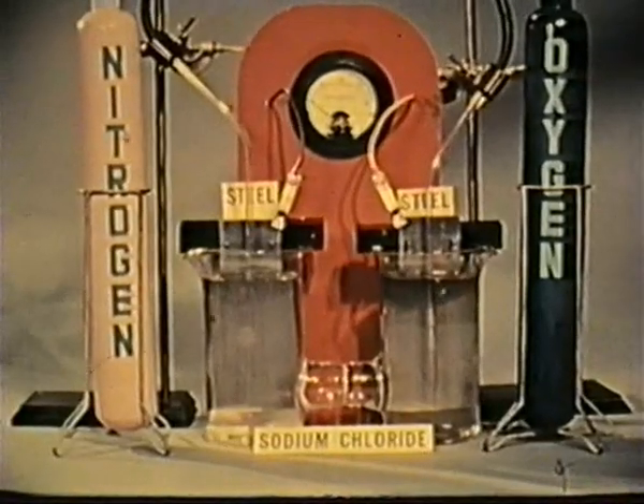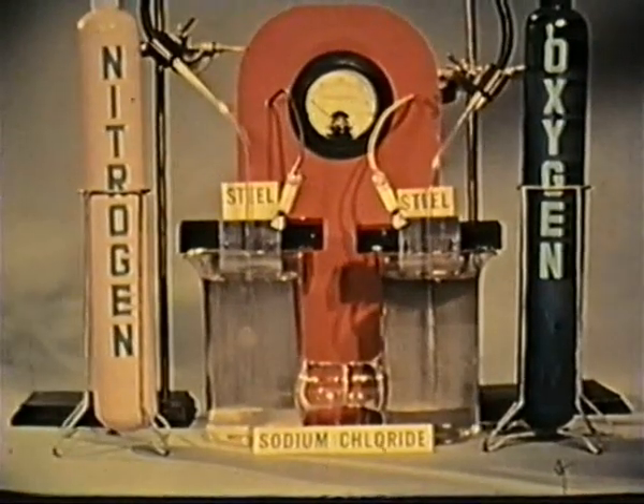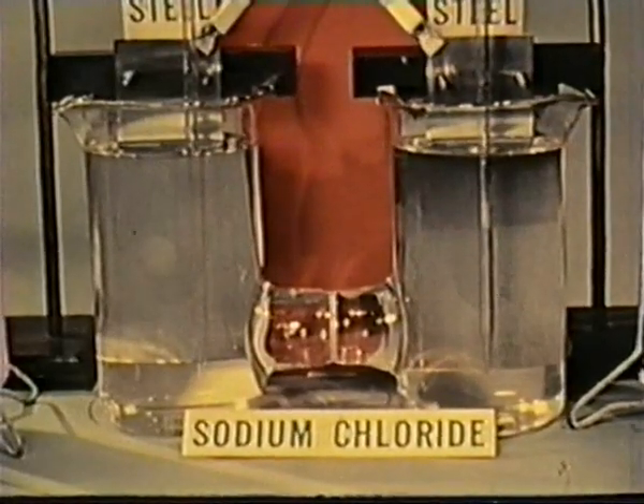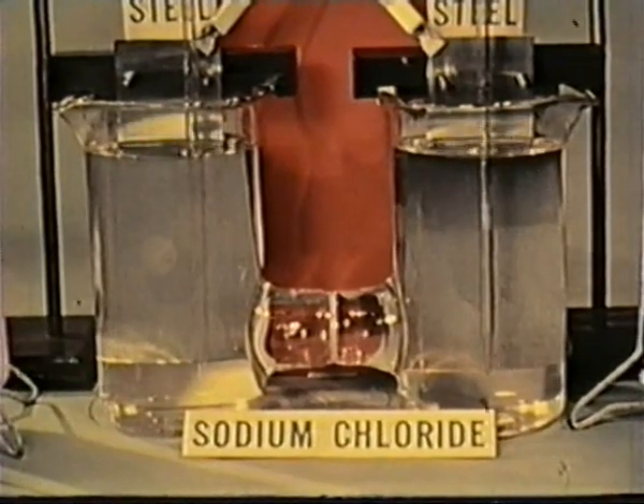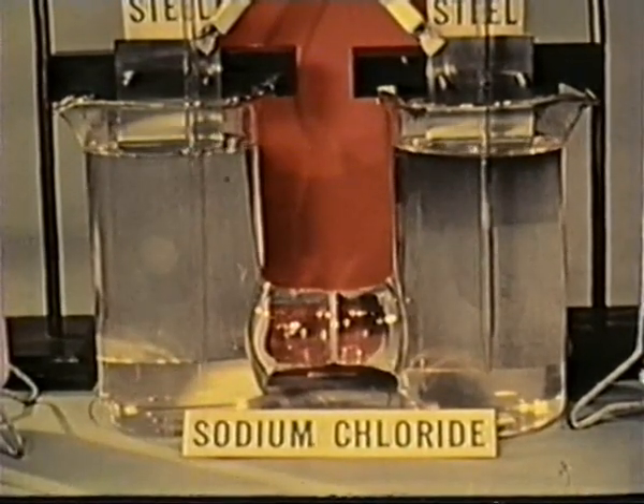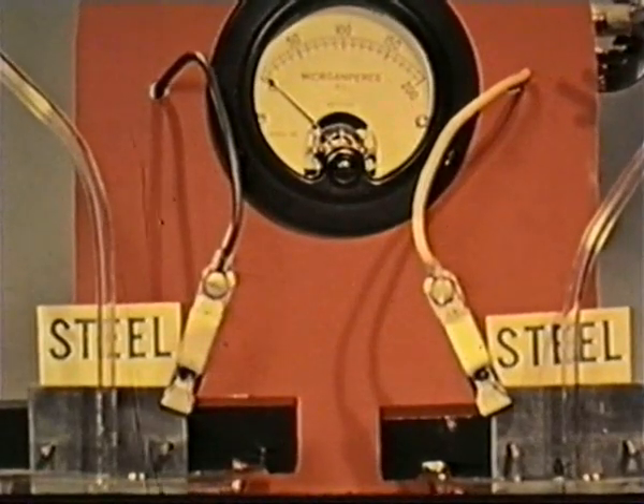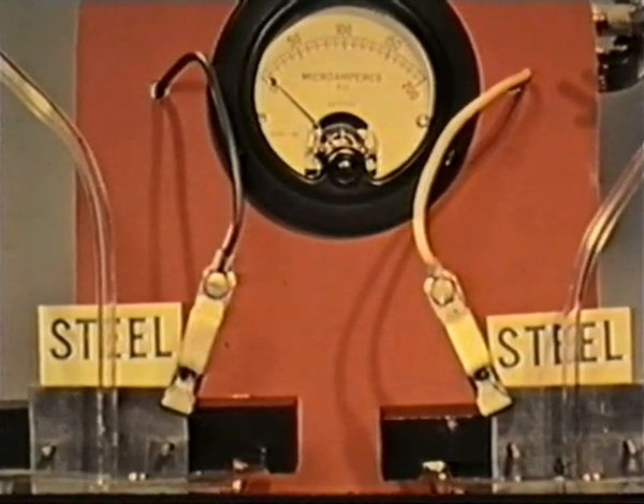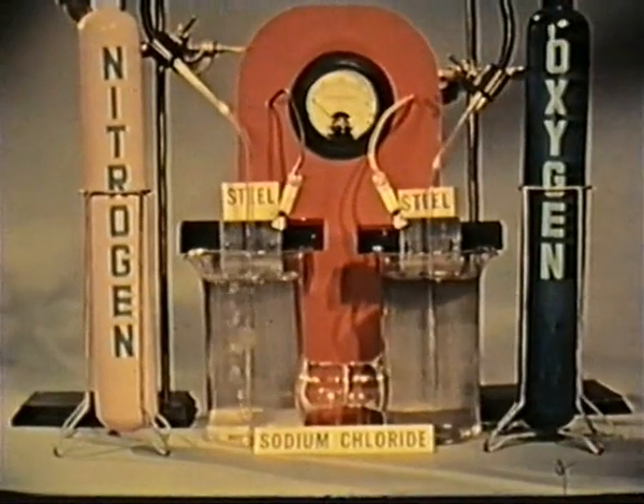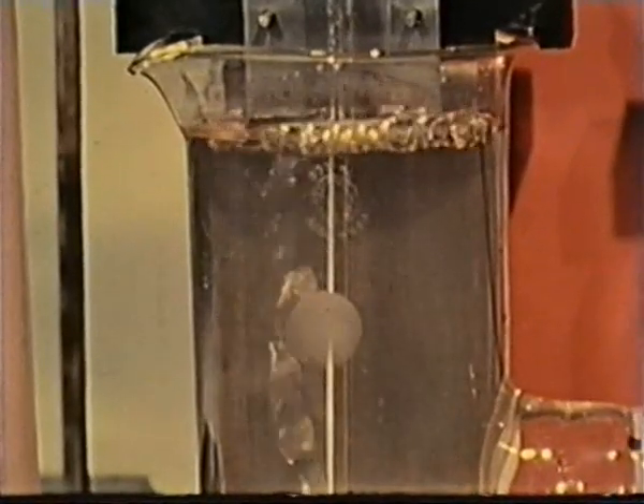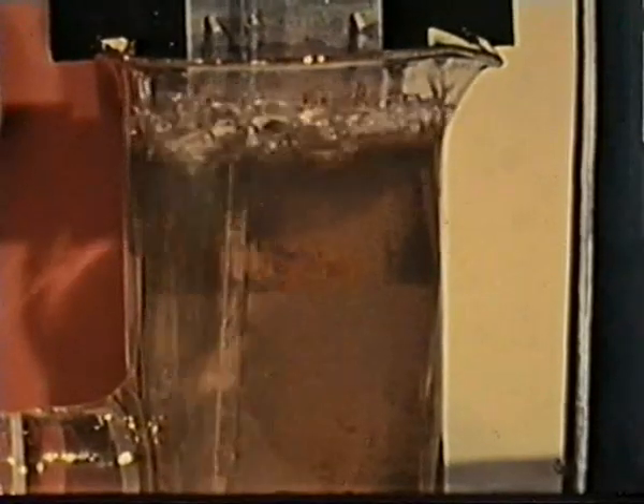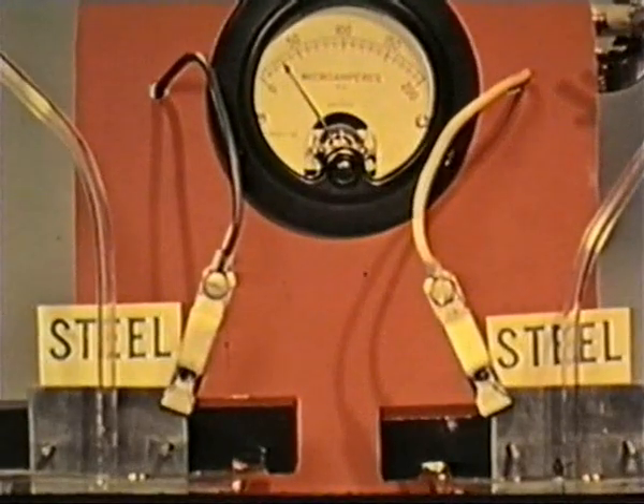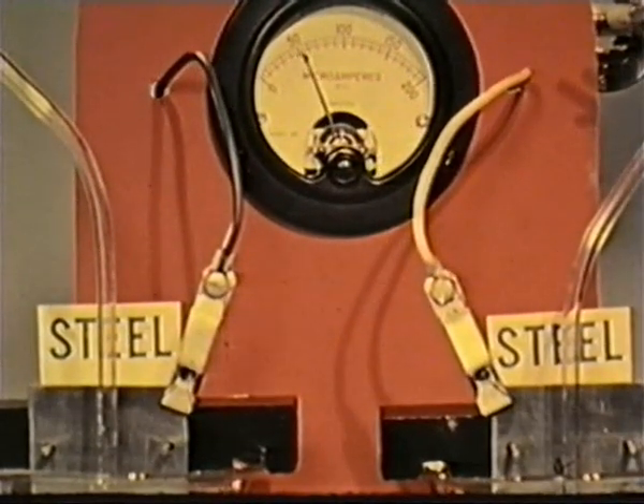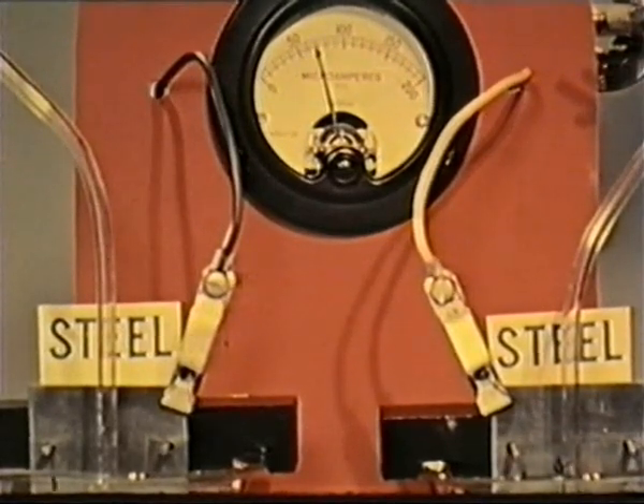The fact that electricity does flow between points where oxygen concentrations differ may be demonstrated with similar pieces of steel in each side of a two-compartment cell containing a dilute sodium chloride solution. No current flows when they are coupled through a microammeter. But if we bubble nitrogen through one side of the cell to reduce the oxygen concentration and oxygen through the other side to increase the oxygen content, we find electricity flowing with the steel and the electrolyte starved of oxygen acting as the anode, thus proving the existence of a corrosion current.